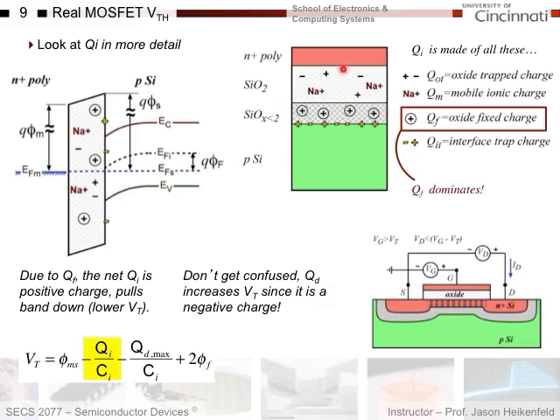So remember, how do we make our dielectric? Well, we started with perfect silicon. Then we expose it to oxygen or moisture, which oxidizes it and basically goes deeper and deeper into the silicon, turning into oxide. If you look here at the interface, the oxygen has to diffuse through silicon dioxide to keep growing deeper and deeper into the silicon, right? To keep basically making a thicker layer of rust.